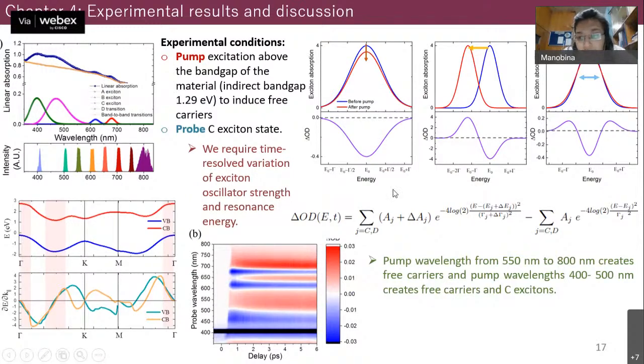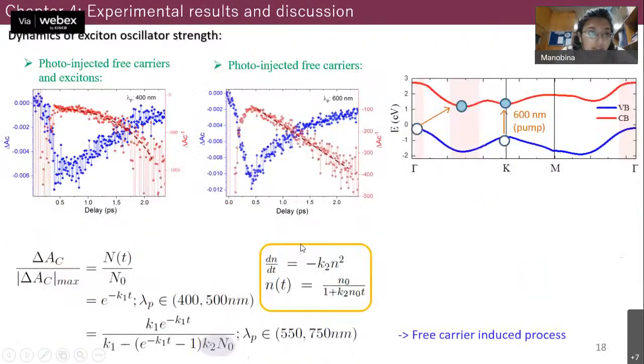And this is the model that we consider to find out the temporal evolution of different excitonic parameters, mainly this absorption oscillator strength, resonance energy, and the line width. So over time, we use this model to find out parameters. So next, I'll just briefly tell about this oscillator strength dynamics first. So this oscillator strength dynamics is dictated by a second order equation. So dn/dt proportional to n squared. So that's why the inverse of the carrier dynamics follows some linear relation.